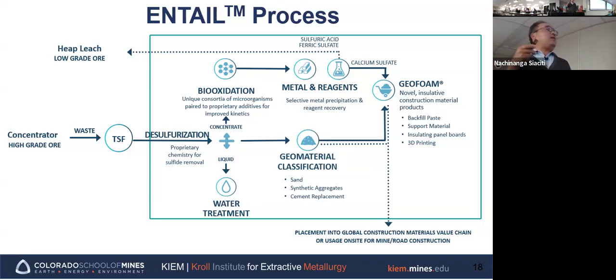Most large copper mines have heap leaching and dump leaching operations, so they can use sulfuric acid and ferric sulfate. And then we can make the GEOFOAM using the tails of the tails, which is cleaner because we get rid of the sulfide, pyrite, and also some other toxic sulfide-associated elements such as arsenic, cadmium, nickel, cobalt, zinc, and all the other metals. So the application of this whole process is to reutilize the tailings, supply the key lixiviants, and make new construction materials that can be used for backfill, support materials, and insulating material.